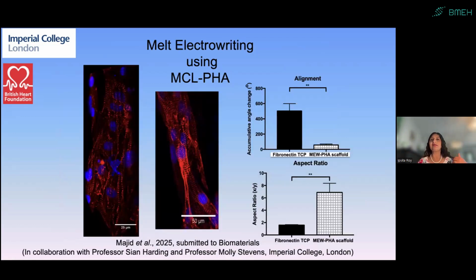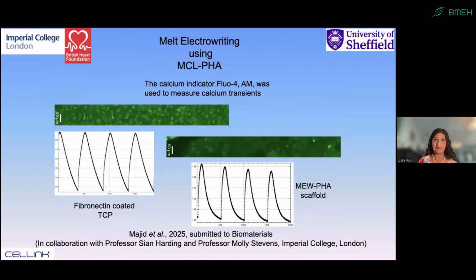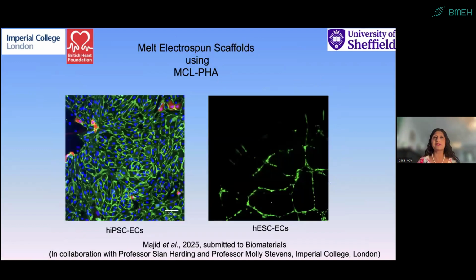So you can see here that there was a beautiful anisotropic development, and these were highly mature cardiomyocytes that we found. And when we looked at calcium transients, which is the main functional assessment of cardiomyocyte functions, we observed that we had excellent, normal calcium transients.